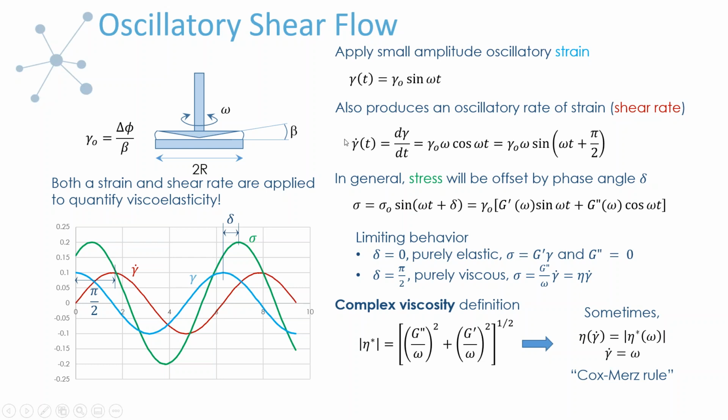So the beauty of these experiments really is that because it's a time-dependent strain, that means we're also applying not just a strain like you would for analysis of a solid or elastic material, but we're applying a rate of strain or shear rate because it's time dependent. If you remember, we can get the shear rate or rate of strain by taking the time derivative of our sinusoidal strain, and then this gives us the expression for our shear rate. So we're simultaneously straining the fluid and shearing the fluid. This type of analysis is what you use because you're doing both to the fluid.